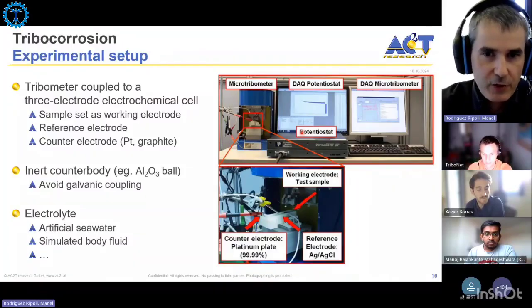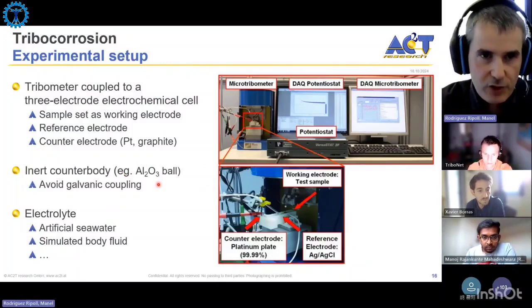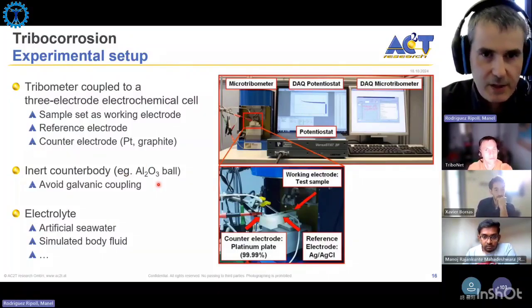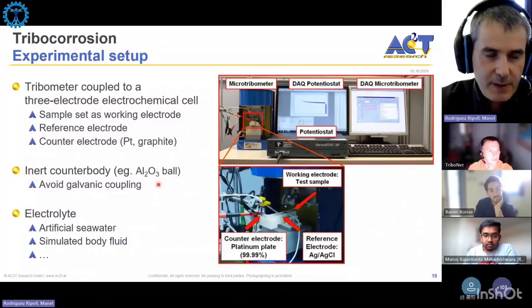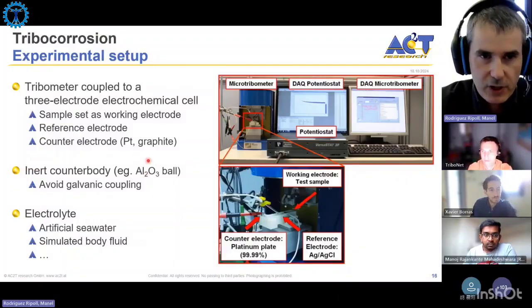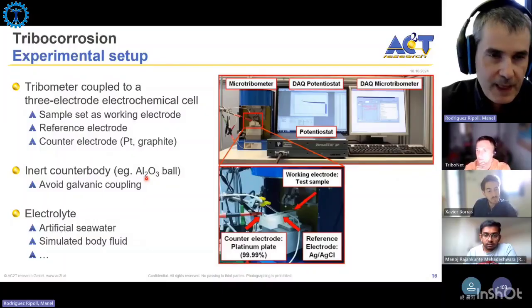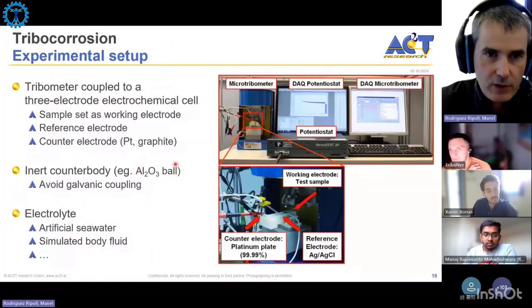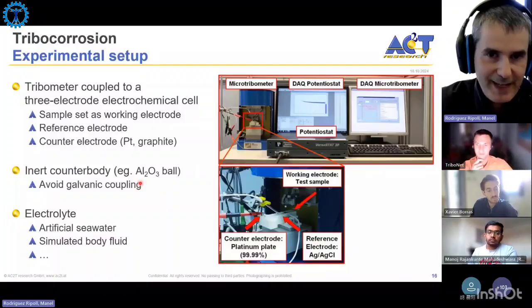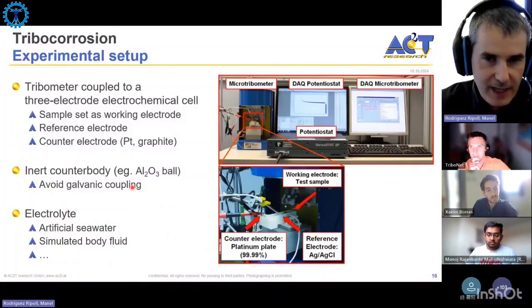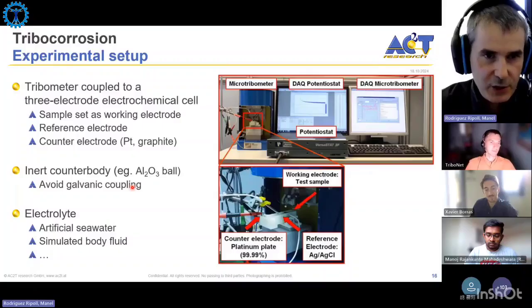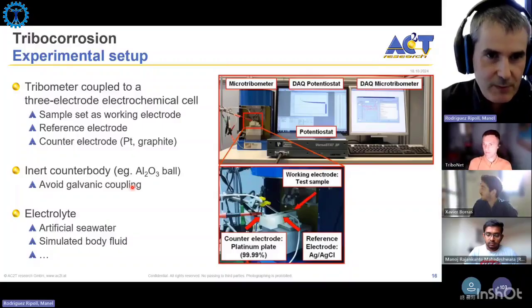What we very often use, this little white fellow here, is an aluminum oxide ball. Typically in tribocorrosion experiments, we use aluminum oxide or another ceramic counterbody. The reason is that we want a stable counterbody that is not wearing too much. Another reason is that we don't want the counterbody to create a galvanic coupling with our sample, because when you have a galvanic coupling, the cathode and the anode may change depending on which material you use, so you basically change the electrochemistry of the system.